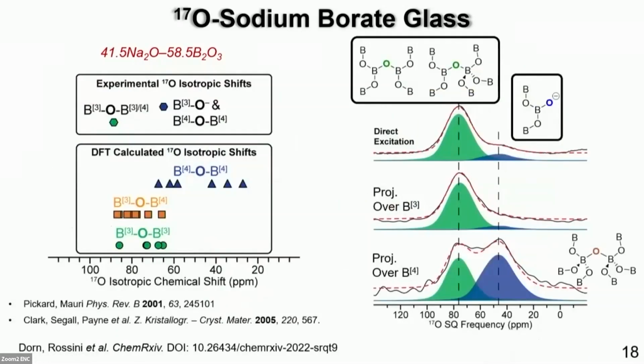We then also performed density functional theory calculations on crystalline borate samples with known crystal structures. And what we see is that on average, an oxygen that bridges between two BO4s exhibits a lower isotropic chemical shift than an oxygen atom that bridges between a BO3 and a BO4 or two BO3s. So therefore, we are assigning this kind of unexpected correlation to an oxygen atom that is bridging between two BO4 units.